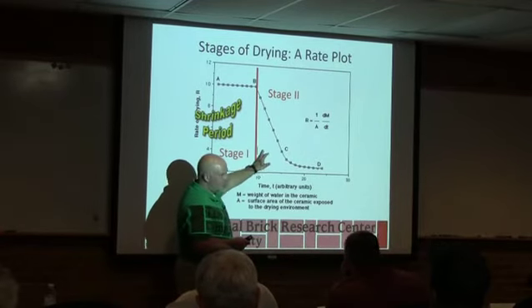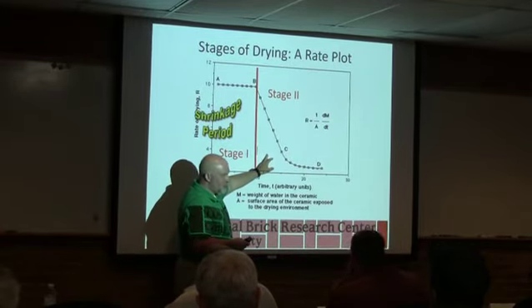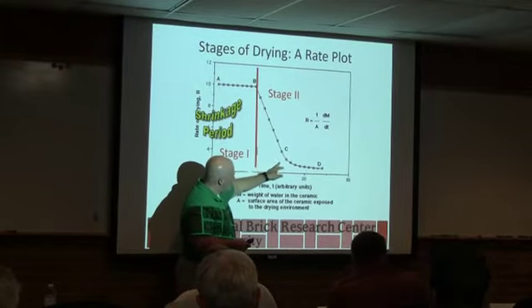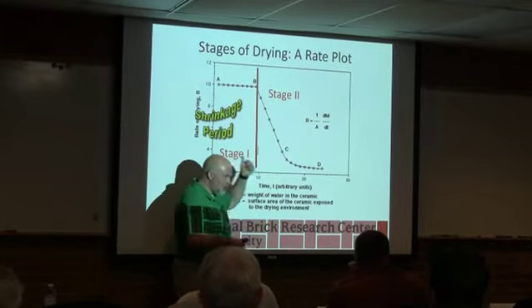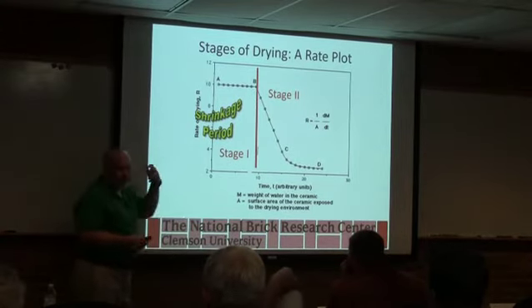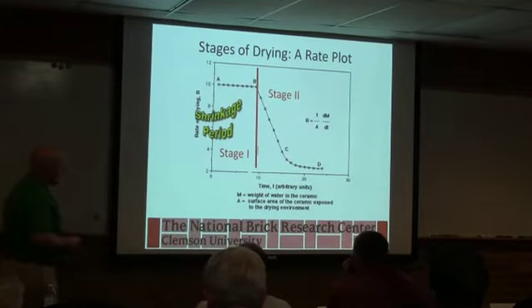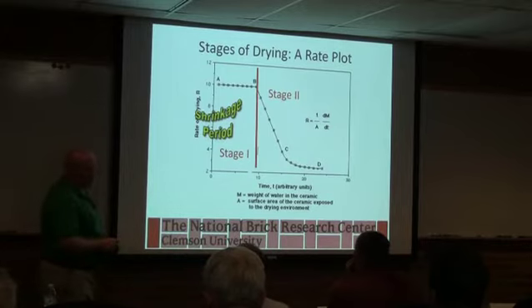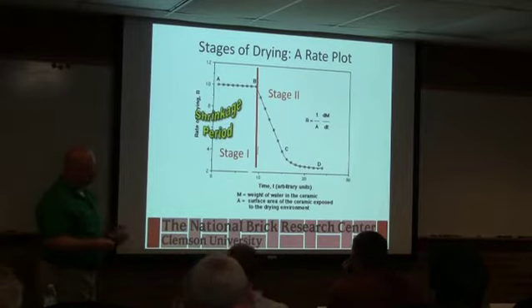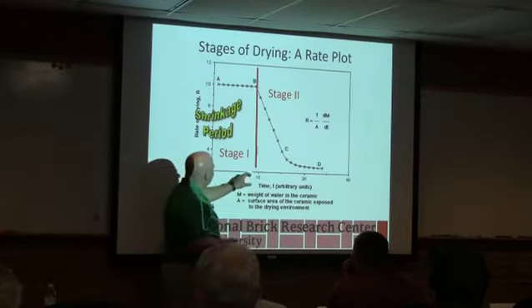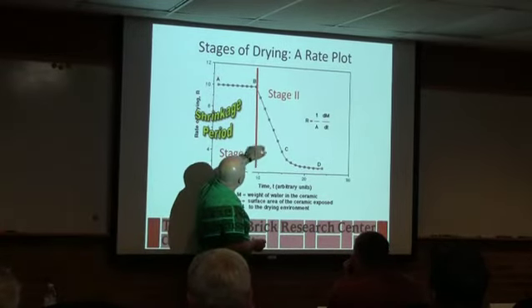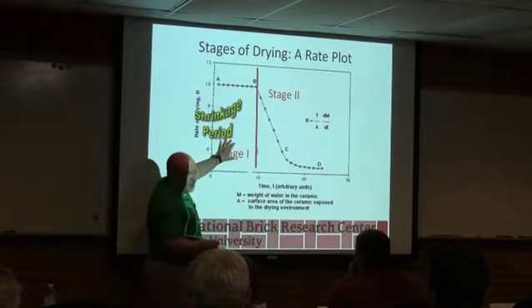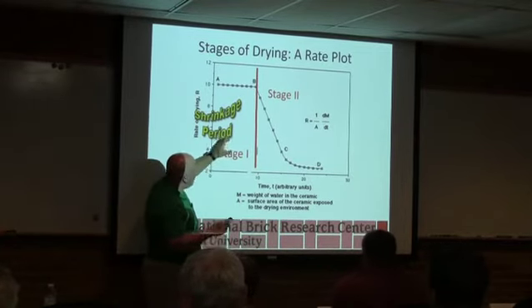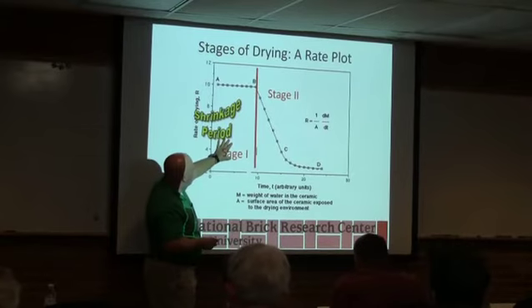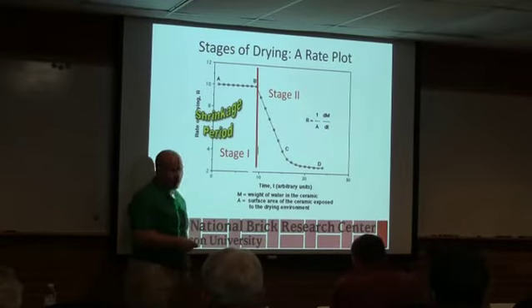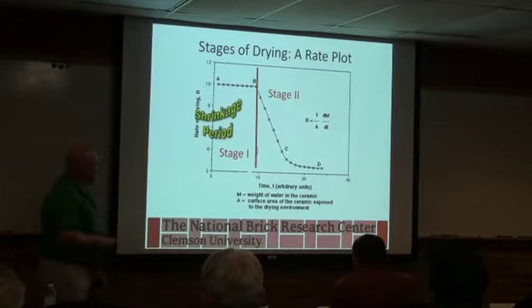Once shrinkage stops, the evaporation starts to take place below the surface of the brick. And the further you get into the brick, the longer the water has to travel to get out. Okay, so that's another complication there. So that's where we talk about open body, closed or tight body. It has to do with how easy it is to get the water out down here. Typically, when we're controlling this, we also try to open the body. Usually you're adding a grog or some coarse particles. You're reducing the total amount of shrinkage too, so you make it a little easier to dry.